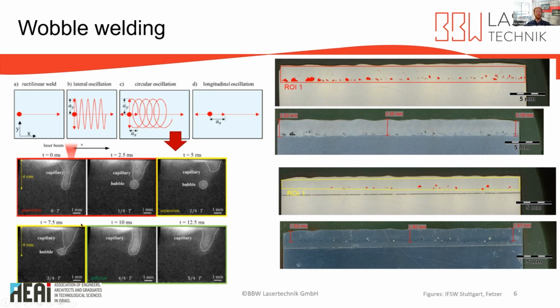As you can see in this image, there is still the pore formation during wobble welding. But by using a circular oscillation geometry here, the beam passes over the same position several times and interacts with possible bubbles multiple times. And this leads to them disappearing by degassing back into the capillary and is the reason for significant pore reduction. And on the right side, you can now see some cross sections we have made.